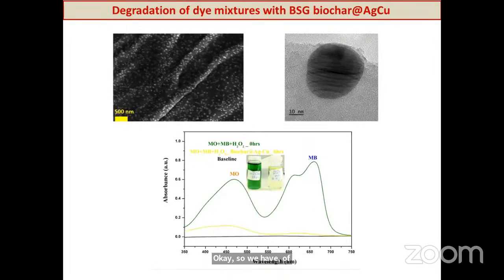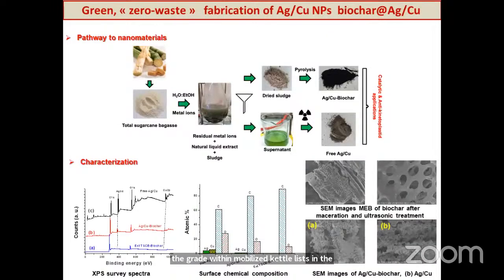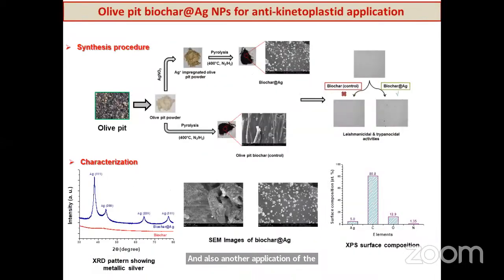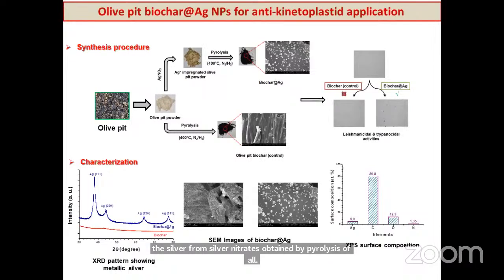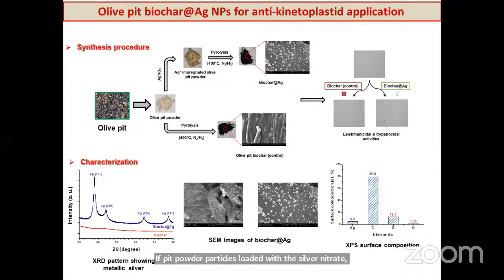Okay, so we have, of course, studied the brewer spent grain with immobilized catalyst in the degradation and mineralization of dyes. And also another application, because I'm running out of time. Here, for example, we loaded silver from silver nitrate obtained by pyrolysis of olive pit powder particles loaded with silver nitrate. We obtained biochar with immobilized silver nanoparticles, and we have employed these nanoparticles in the treatment of